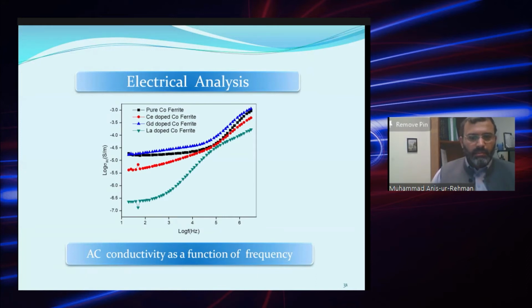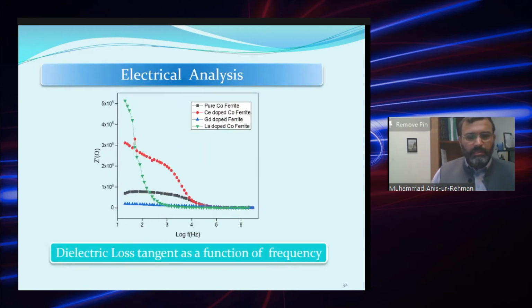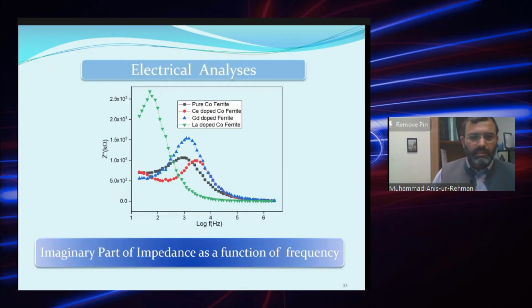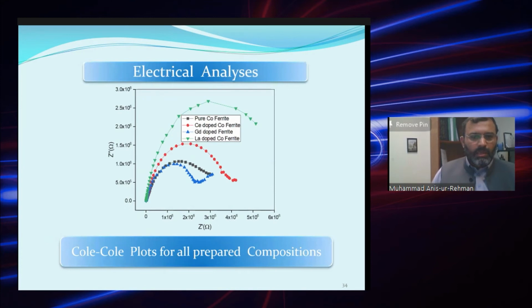You see in this diagram that as we are increasing the frequency, the conductivity in the frequency dependent region is increasing, in a similar way as you see in the previous slide, since more successful hoppings are done as compared to the lower frequencies. Impedance is the inverse of the conductivity, and it is decreasing as we are increasing the frequency. In the Cole-Cole plots, we can see that the conduction behavior in these materials is of Maxwell-Wagner type. The double layer model can be applied, that the grains and the grain boundaries are contributing in the conduction of the materials.